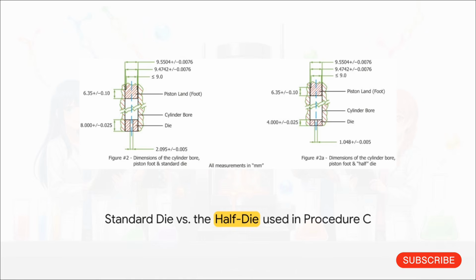The standard bore is about 2.1 millimeters wide. The half die shrinks that opening to just 1.048 millimeters while keeping the exact same length to diameter ratio. This creates the extra resistance needed to get accurate readings on incredibly slippery, fast-melting polyolefins.